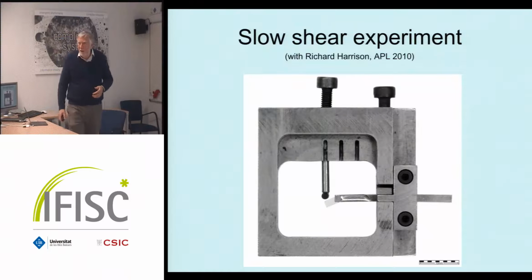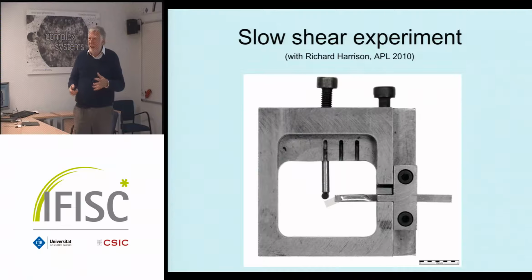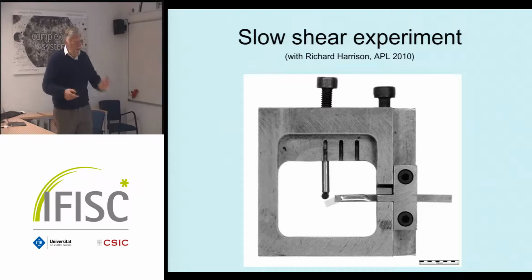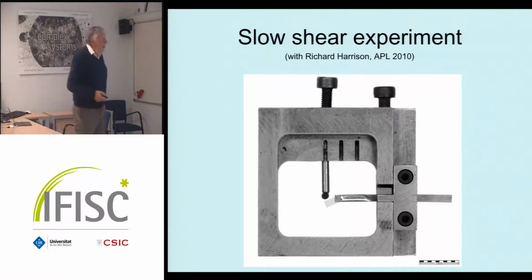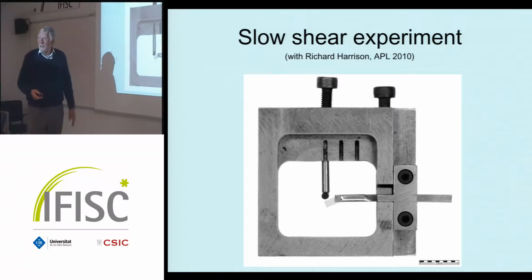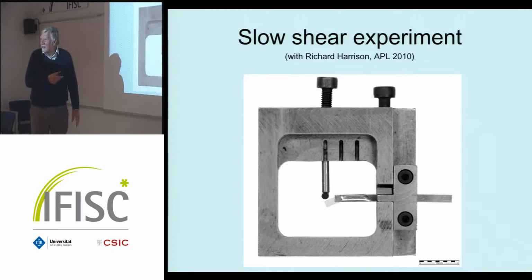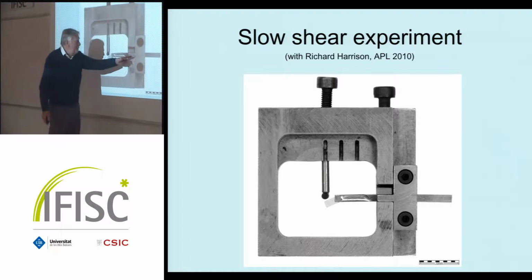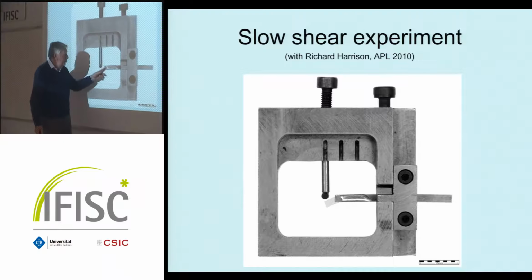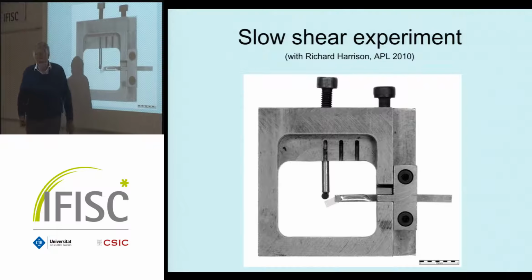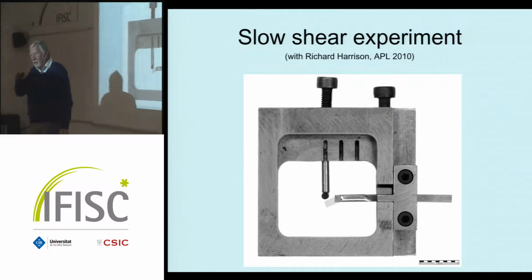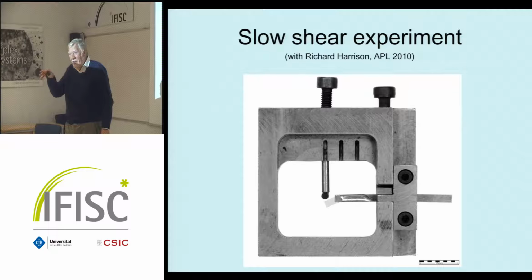Now I like small experiments. In particular, my size discrimination thing is if I can put an experiment in my pocket. And this one is a pocket experiment. This one, that's about the size. And so it looks really quite primitive, right? It's almost for mathematicians, something like this, right? So what you do is you have here a crystal holder, and you stick on with glue. Here's the crystal. And then you poke the crystal down and shear it and see how these functional interfaces are now moving, because you can make them move, because twin boundary can move.